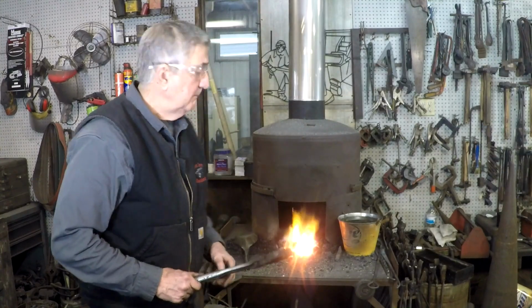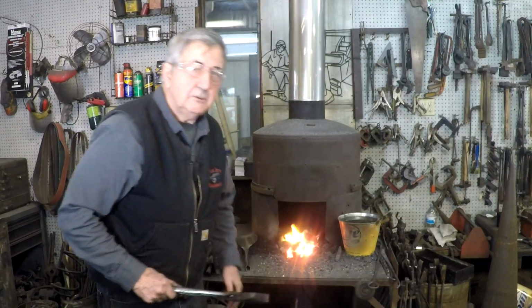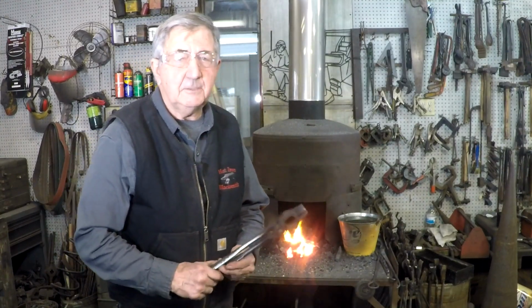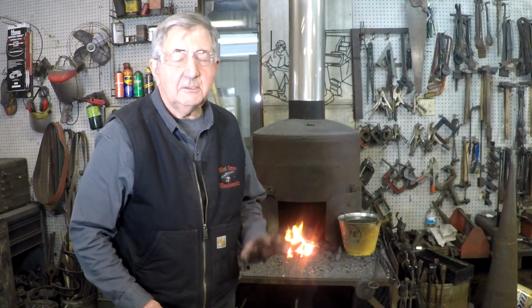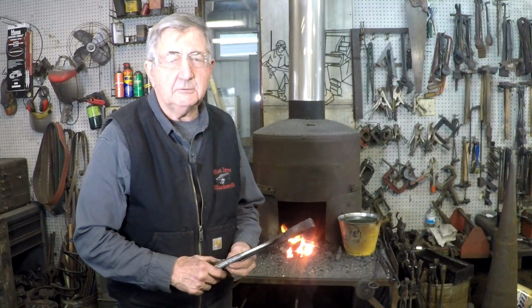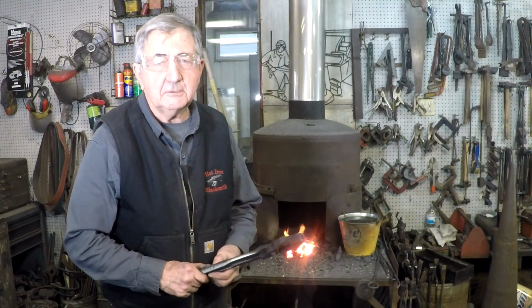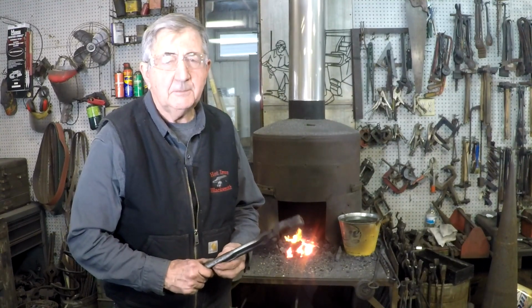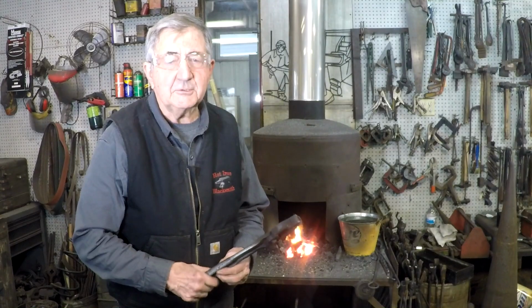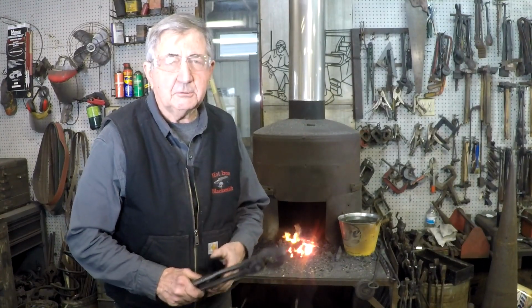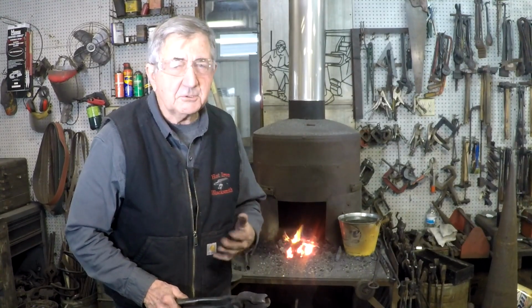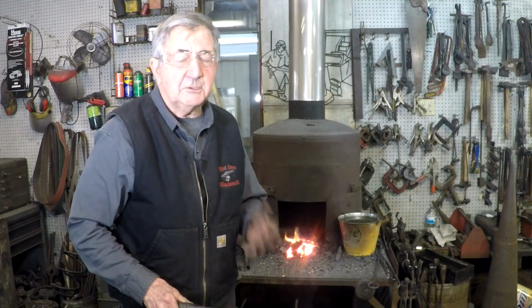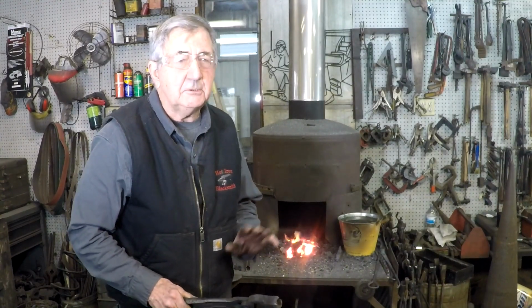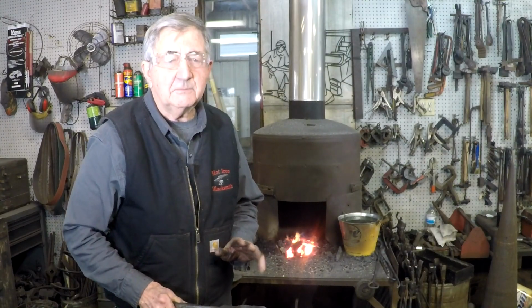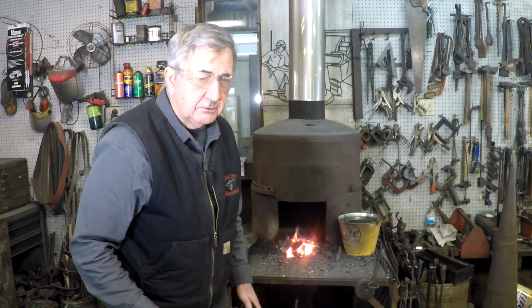The annealing, I show by bringing it up to a non-magnetic temperature, checking that, and then letting the metal cool down to room temperature, or at least down to about 300 degrees. That makes sure that there are no other metallurgical changes occurring within the structure of the steel. Once it gets down to 300 degrees for this steel, it's basically uniform and without any further change.